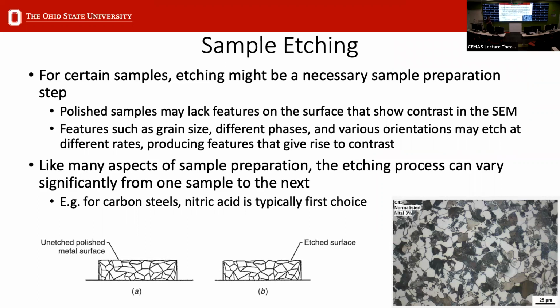I mentioned earlier that some additional steps might be needed for sample preparation. For a lot of the metallographic work, sample etching is needed to gain contrast. If you have your sample mirror polished, you might have very few features that might generate contrast in the SEM. In this case, you can use etching that will remove material at various rates. Etching, depending on how you do it or the chemical you use, varies significantly from one sample to the next. This can vary based on different compositions in your material, different phases, and different orientations. That all affects the etching rate.